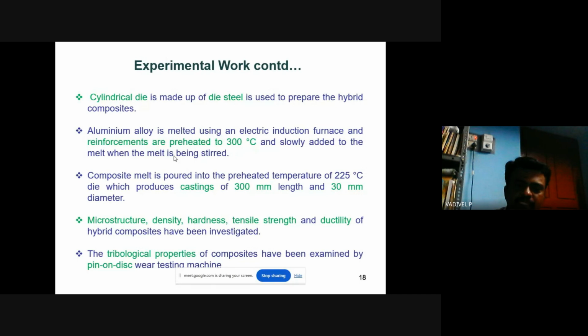So it breaks like a brittle material. The titanium diboride is not fully mixing with the aluminum alloy. After preheating, at the time of the seventh trial, we used the preheated material, so the bonding is very good between the aluminum and the reinforcement material. After preheating to 300 degrees Celsius, the reinforcement is slowly added to the melt, and it is stirred at a speed of 800 rpm.